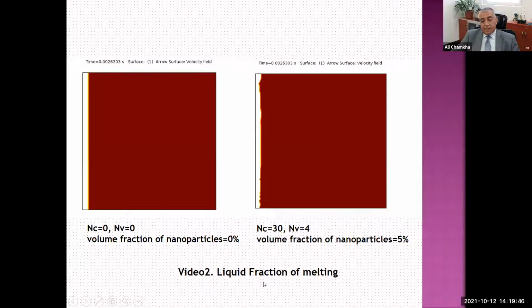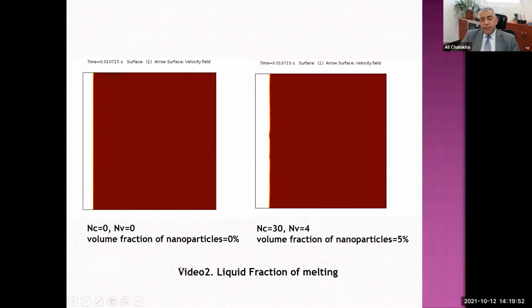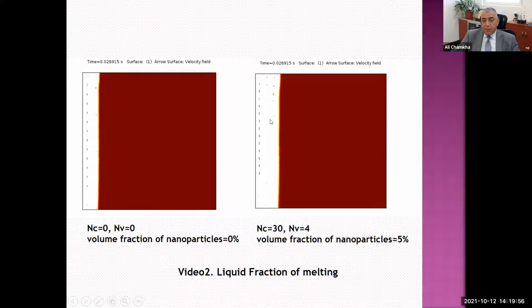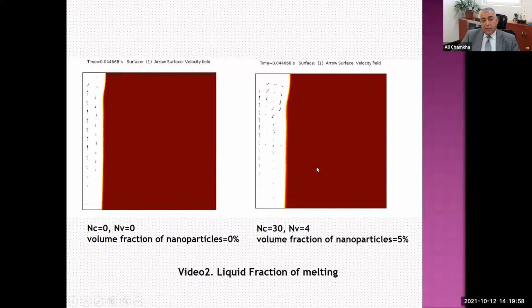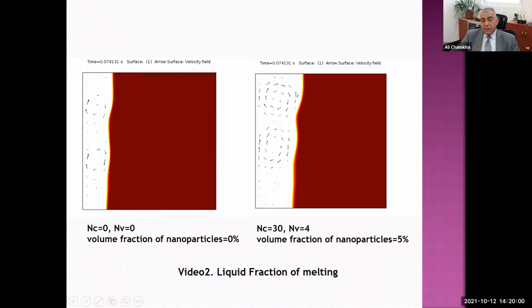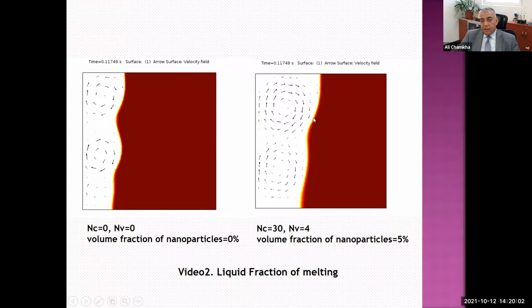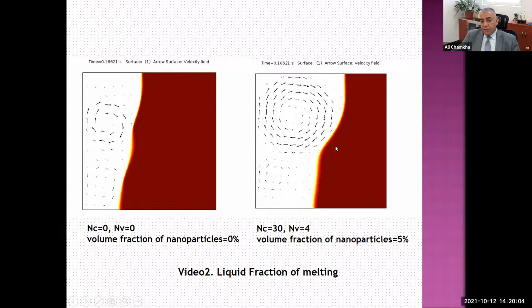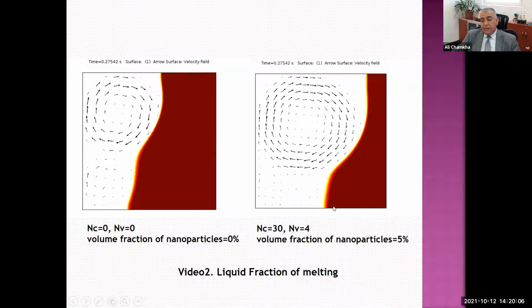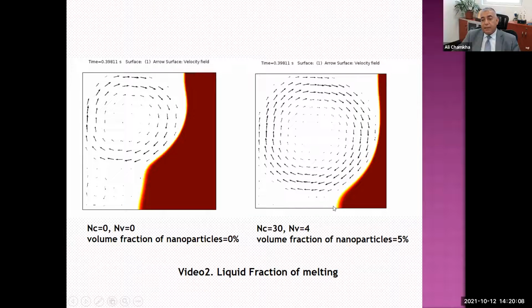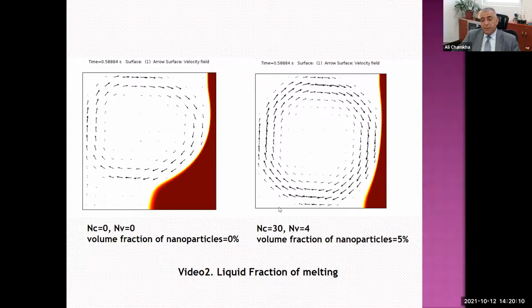And this picture was the liquid volume fraction. If you want to see it, we can see it one more time, as it is important. And you can see here the formation of the recirculation zones, and you're melting quicker than here. The mushy zone is here. Then you start movement, and then you can see this line. And then you finish it with only 5% of nanoparticles.